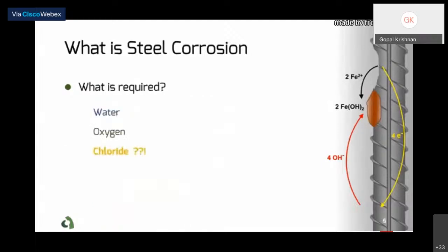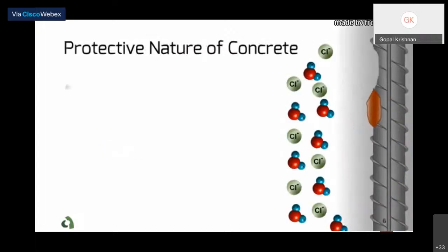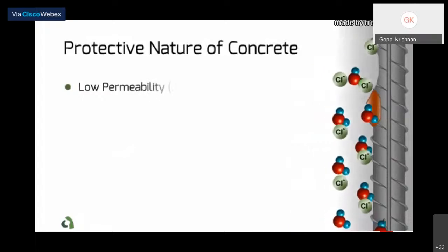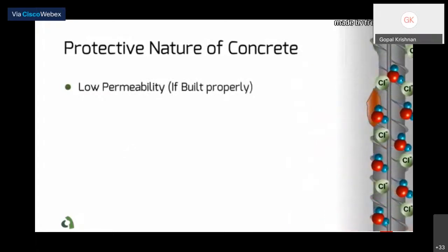We know that the availability of these three elements are essential for corrosion to happen. The reaction requires water and oxygen. However, experiments in real case scenarios show that chloride plays a key role in the onset of corrosion. Concrete provides a high alkalinity environment around the reinforcement. In normal conditions, one can expect this will protect the reinforcing bars from corrosion. At the same time, we know that concrete is a permeable material, as moisture and aggressive ions can move through the pore structure of concrete.